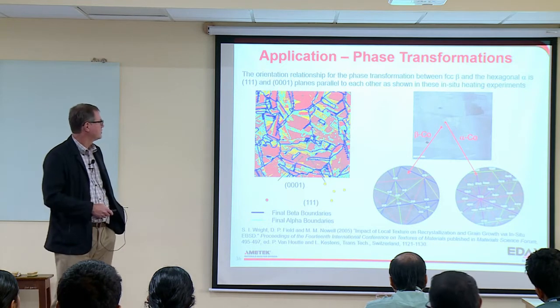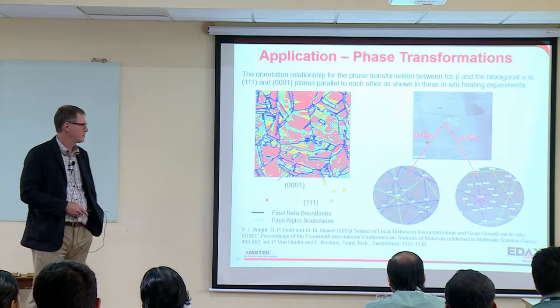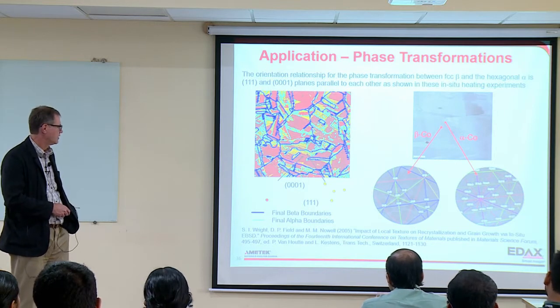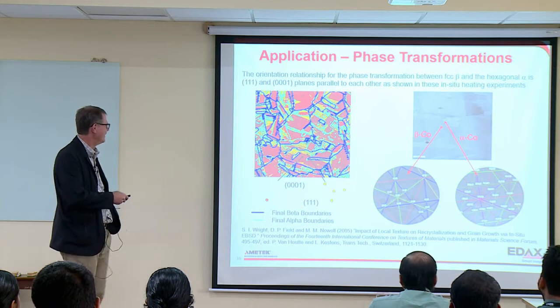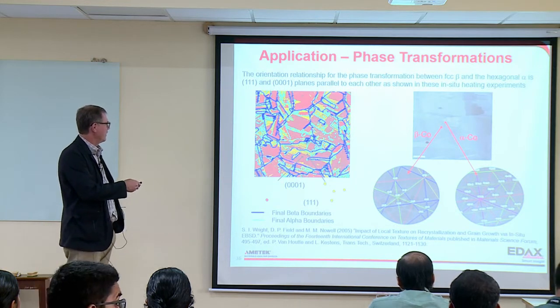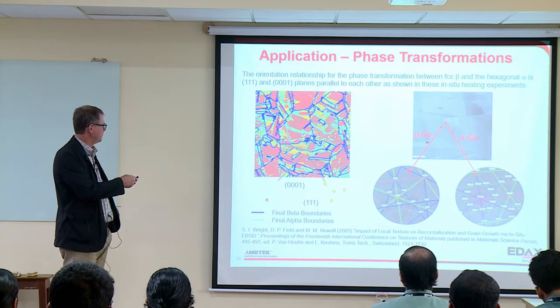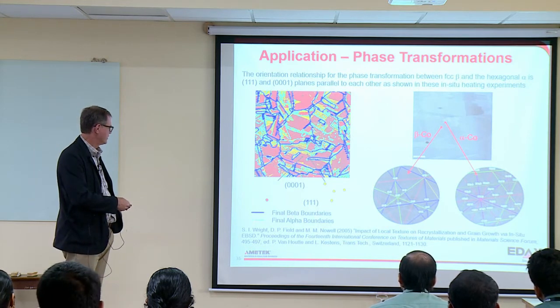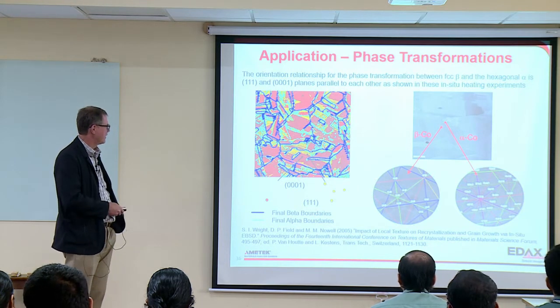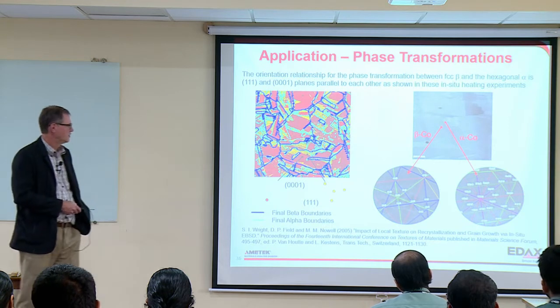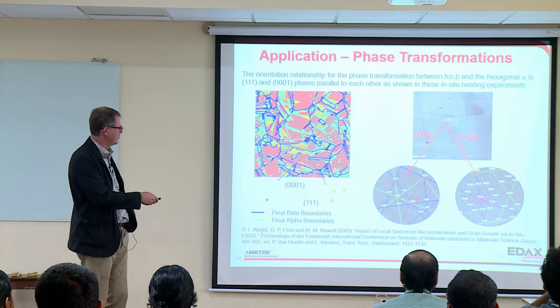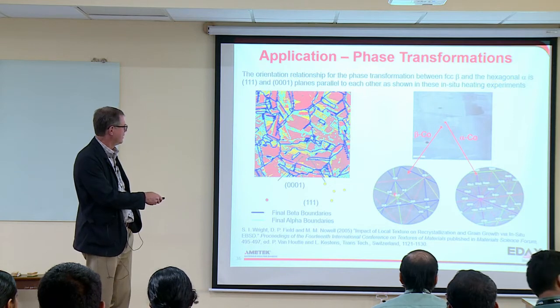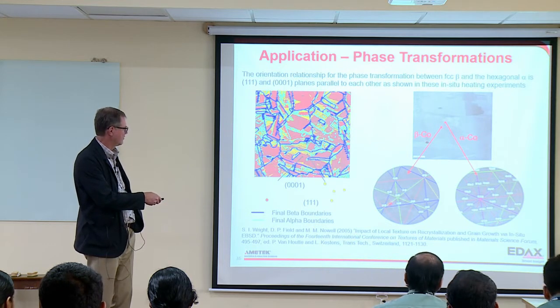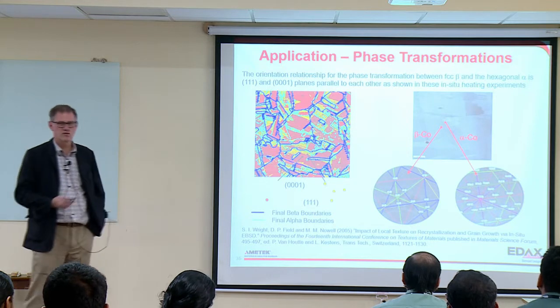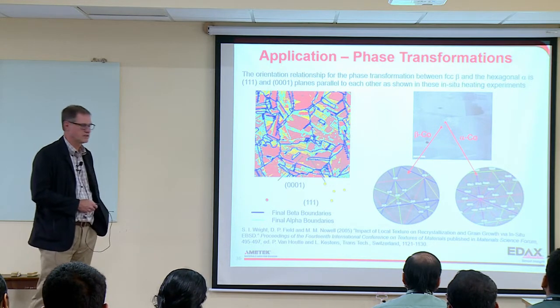Another area is phase transformations, and we can see these in EBSD. This is some in situ work I did with my colleagues, almost 20 years ago now, or 15 years, I guess. What you see here is the blue boundaries are the final beta boundaries, and the cyan ones are the final alpha boundaries, and we track that as we heat the material. What's interesting to me is that you can see here's the 111 plane in the beta phase. This is in cobalt, and the basal pole in the hexagonal phase, and they're right on top of each other. So you can see this phase transformation going as expected. This was mostly a test for us to make sure that we could do in situ work.